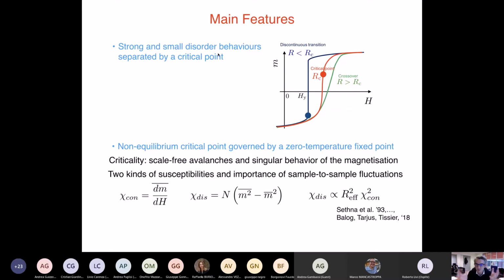So this is the very first important feature, and one can understand it as follows. Of course, if the disorder is super strong, then the interaction between the spins is not important, and you have a smooth curve. But if the disorder is very small, then the negatively magnetized state will at a certain point destabilize completely, because if one spin flips, all the neighbors have a tendency to flip because of the ferromagnetic interaction, and then the neighbors of the neighbors will have the tendency to flip, and so there will be a big jump of the system, which is what you see in the discontinuous blue curve. So this is the first thing.